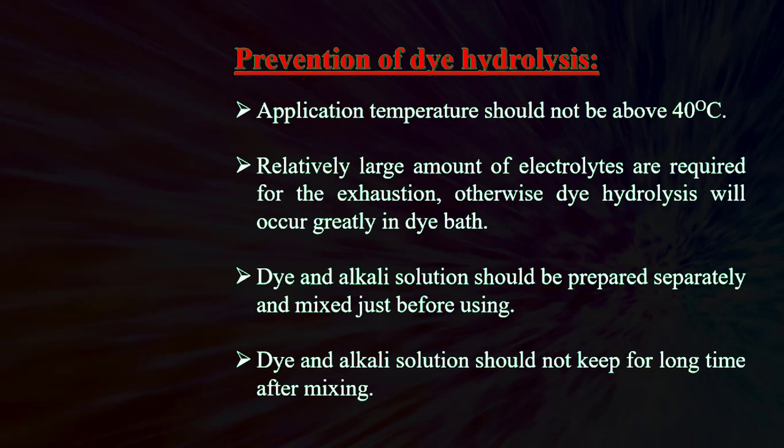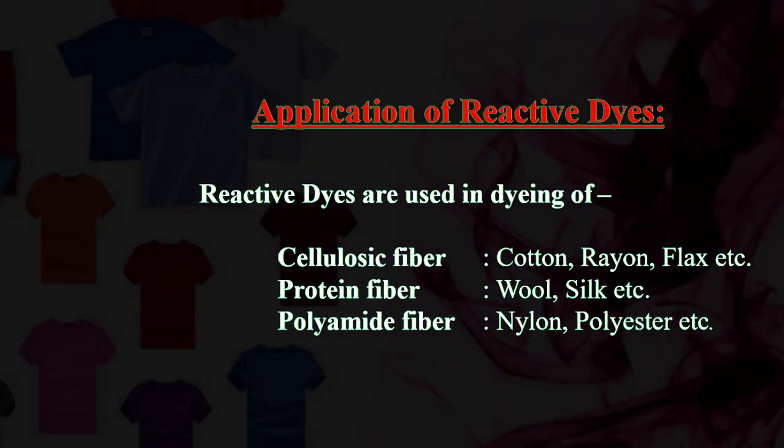Prevention of dye hydrolysis: Application temperature should not be above 40°C. A relatively large amount of electrolytes is required for exhaustion, otherwise dye hydrolysis will occur greatly in the dye bath. Dye and alkali solution should be prepared separately and mixed just before use, and the mixed solution should not be kept for a long time.